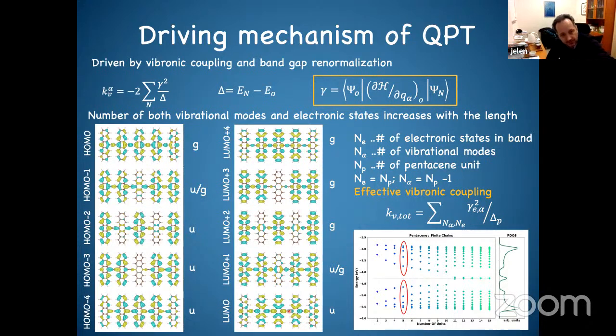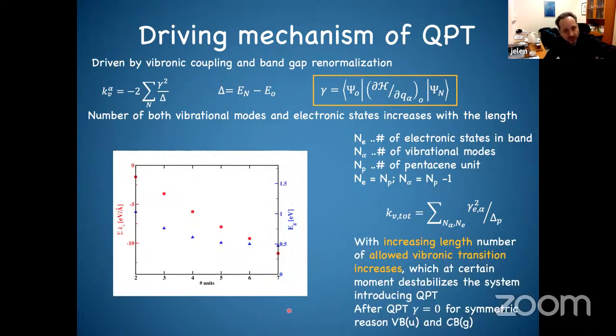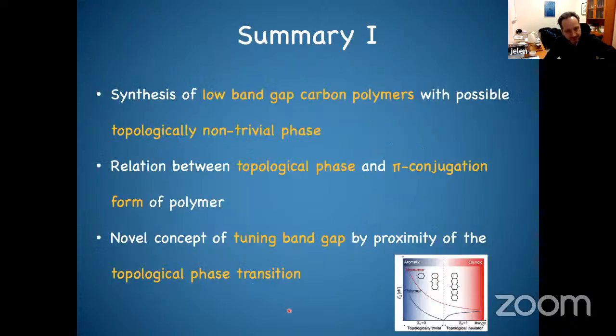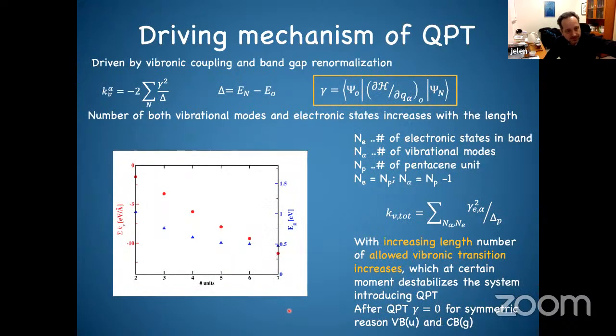If both were of the same symmetry but opposite, there would be no vibronic coupling. So the system, with these vibronic couplings, wants to purify this band to keep the same symmetry. Now we can calculate it. We did this calculation for all these many bands, and what you see here is that the total vibronic coupling, this number of units, is increasing.